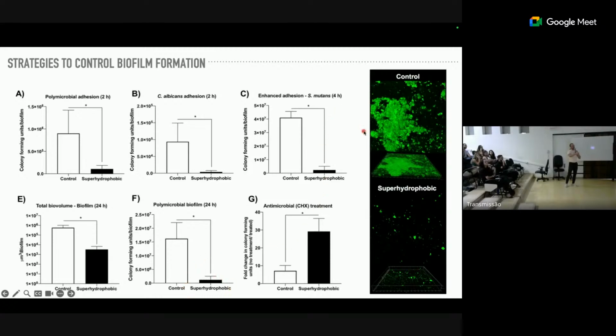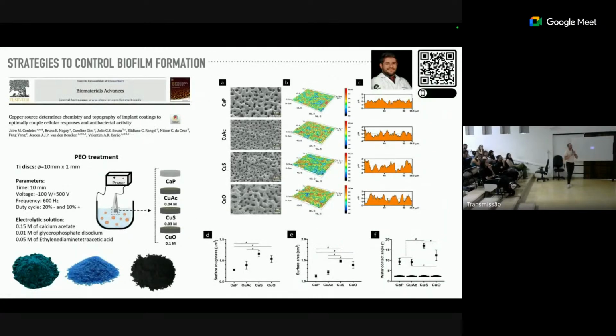We also checked in confocal images. You can clearly see in green the polymicrobial biofilm. In the experimental group, we have a lower content, and this is the quantitative data of this confocal. We also checked if you treat this biofilm, here in control and here in the superhydrophobic, with chlorhexidine, a very common antimicrobial agent used to control peri-implantitis, we can see that the effect was more prevalent in the superhydrophobic surface.